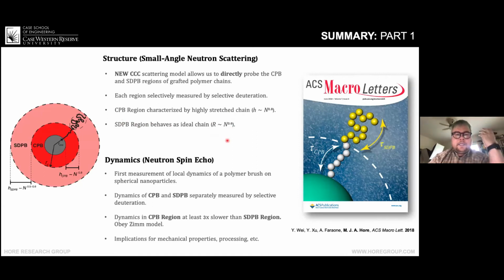To make sense of the observations that have been made experimentally about the dynamics, we performed the first spin echo measurement of the local dynamics of a polymer brush. And this is a unique capability of neutron scattering that again results from us being able to selectively deuterate the 2 regions. The dynamics in the concentrated region were at least 3 times slower than that of the semi-dilute region. And so that explains why when you have shorter chains, you see such a huge difference between the grafted chains and the free chains, whereas when you start increasing the molecular weight of the brush, the 2 start behaving more similarly to each other.